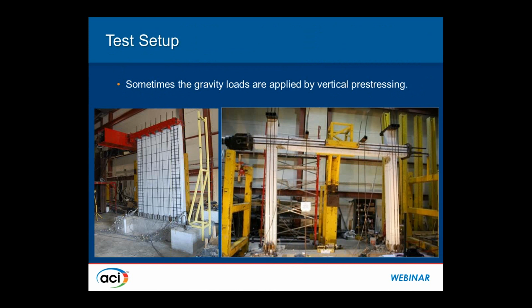This is a convenient way of applying axial load, so long as one keeps track of changes in the pre-stressing stress, because under reverse cyclic loading, one side may lose a little bit of load, the other side may gain a little bit. So long as this is monitored, it's a convenient way of applying axial load. Now, axial load obviously does have a very significant effect on performance of these specimens. Where we are concerned with ductility, axial load tends to reduce ductility, because then concrete becomes more dominant in response, and that has to be considered.